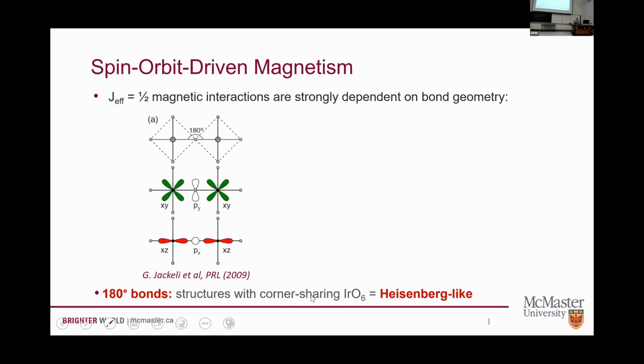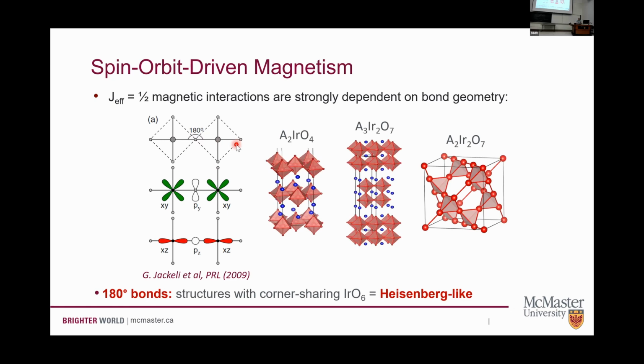So the interesting stuff happens when we start to put these J effective 1/2 isospins onto different lattices or different crystal structures. One of the common geometries that we can come across is this one. This is a case where we've got IrO6 octahedra that are connected by the corners. In this corner sharing geometry, we get a bond angle of 180 degrees from iridium through an oxygen to another iridium. And you can show, if you calculate these sorts of things, that this kind of 180-degree bond gives you what are basically Heisenberg-like interactions. This is a geometry that we see in layered perovskite materials or bilayered materials, or the pyrochlore lattice that many of us here at McMaster know and love. And so again, the dominant interaction here for these 180-degree bonds is a conventional Heisenberg-like interaction.